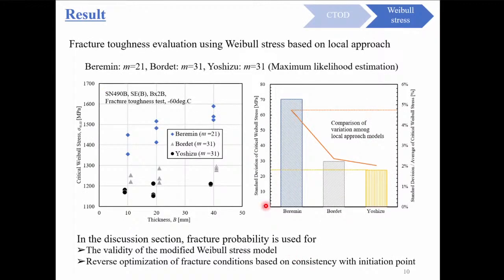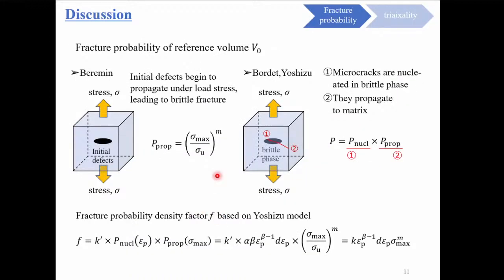It was found that Bordet and Yoshizu models could evaluate the fracture toughness uniformly, modified from the original Beremin model. In order to evaluate the validity of these Weibull stress models, we defined the probability that a given volume element would be the fracture initiation point for the entire specimen by going back to the derivation of each local approach, assuming that